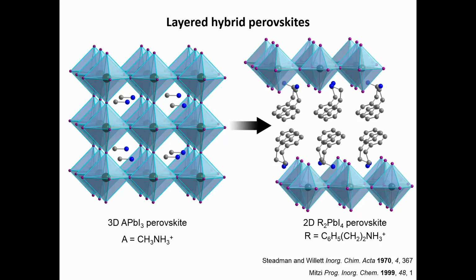And then we took that same composition and we crashed out the crystals as fast as we could, without allowing for any kind of correction. Usually you get much more defects when you crystallize something quickly. We took these materials and we pulverized them in a ball mill, just beating it up. We did everything we could to mess with the defects, and it didn't change the emission in any way.